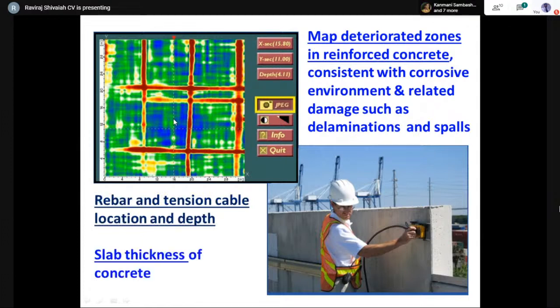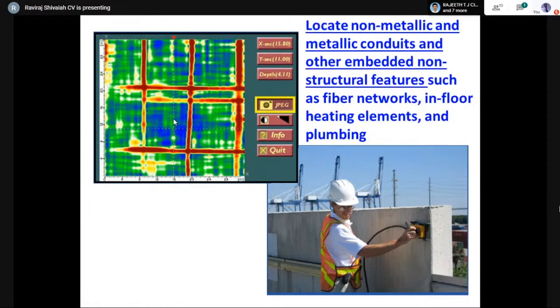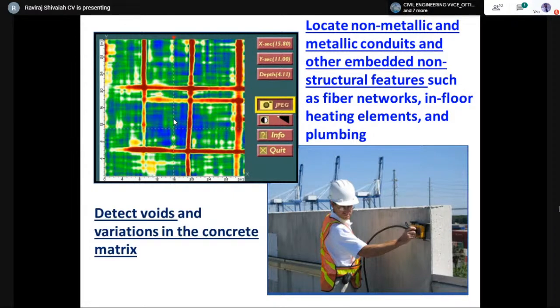You can get the rebars, or your tension cables in case of pre-stressed concrete, and the thickness of the slab. You can locate non-metallic and metallic conduits, like your electric conduits or whatever it is, correct? Fiber networks, heating elements, plumbing elements, detect voids. Variation in concrete mixes can also be rectified. For example, getting a uniform colored pattern in one band and suddenly you get a different colored image. So we can clearly understand that there's some difference in the concrete mix itself. So these are things that can be done.